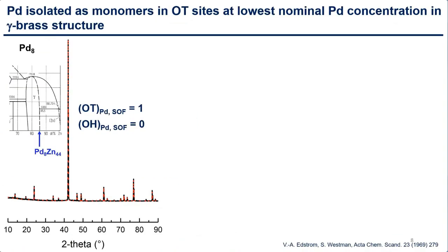So after synthesis of these materials by solid-state diffusion, we need to characterize them to ensure we've achieved the compositional control that we're looking for. The technique of choice is X-ray diffraction with Rietveld refinement in order to confirm composition.